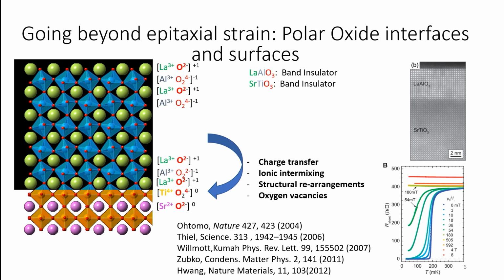And this knob here has really come to the forefront since the discovery of this particular interface between a material called lanthanum aluminate, which is a very insulating material, a band insulator, and strontium titanate, which is also an insulator. So many years ago now, a group, Ohtomo and Hwang, found that when they grew lanthanum aluminate on this strontium titanate substrate, if they grew only a few, 1 or 2 layers of this material, the system was insulating, as you'd expect, because these 2 parent materials are insulating.